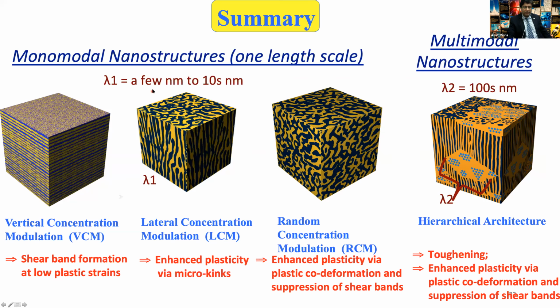But all of these do not increase the toughness so much. By the time when the lambda gets down to a few nanometer, there's limited microstructure designed to enhance toughness. And that required a very different kind of microstructure design, where we, by luck, actually discovered this, and now we can now go back and study in more detail. The hierarchical structure is more promising in enhancing toughness in these structures.